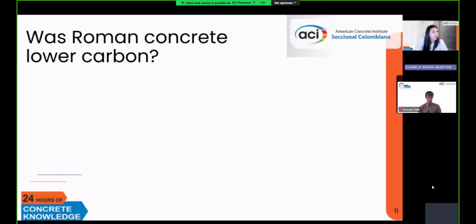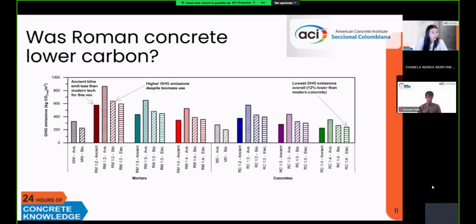And was Roman concrete lower carbon? If we also see this bar diagram that's comparing greenhouse gas emissions on the vertical axis, but this one is looking at each formulation of concrete by cubic meter, so by volume, we can see that the answer was generally no. It was not lower carbon. Under modern production conditions, Roman formulations typically increase greenhouse gas emissions compared with conventional concrete, like we can see again here. These bars correspond to modern formulations, and the color bars correspond to the different Roman concrete and mortar formulations with the different production scenarios. Therefore, the surprising result is that Roman concrete was not necessarily automatically lower carbon or had lower CO2 emissions.